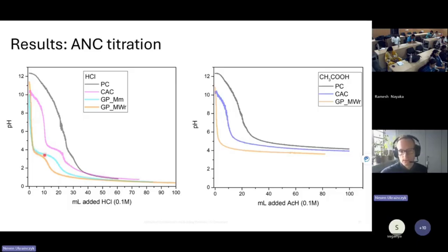Geopolymers, this is the novelty here. The first time I showed also how the geopolymers behave, and actually they have very low neutralization capacity at the beginning, which is basically alkali leaching. The alkalis I showed you before, which are bound to aluminate, which compensate the aluminate charge. So they don't really buffer the pH, very little. And then we have here the silica dissolution, mostly aluminate and silicate aluminate dissolution.